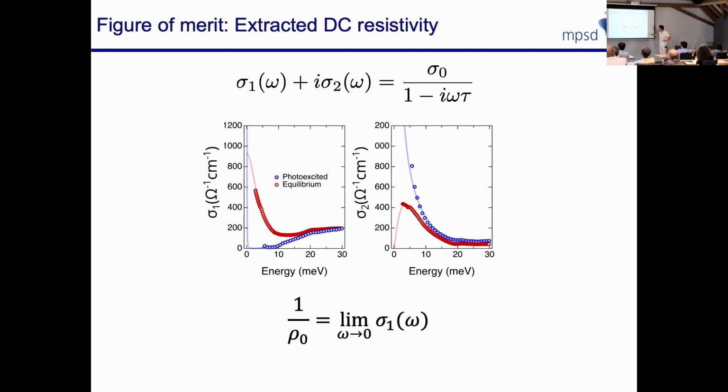Because my data finishes here, I don't know if the scattering rate is zero. The scattering rate is lower than some number down here. This data here is compatible with a scattering rate that is either zero or some small number. This is the data, this is the metal. I know the scattering rate from the metal because I'm measuring it down to a terahertz. And now I refit it as in the other state. I know that the scattering rate is going to become lower than this number, but I don't know exactly how much lower. But I have the same problem.